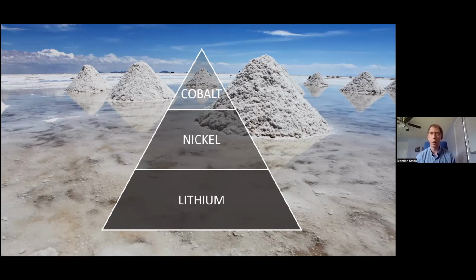So you may know that cobalt is over time being, I wouldn't say phased out, but at least decreased in terms of the ratio in the battery chemistry, largely based on supply chain constriction. About 80% of the cobalt comes from the Congo and under pretty poor humanitarian and environmental conditions. So over time, things like nickel and manganese are increasing in concentration relative to cobalt, but it's still a very, very important critical material.